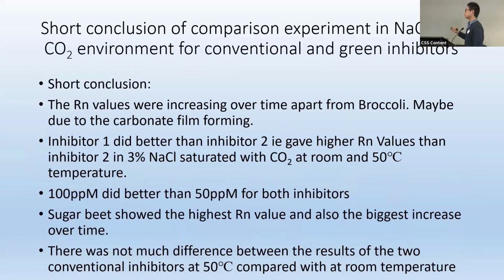So here's the short conclusion, which is like a repeat of things. The Rn value increased over time, probably because a carbonate film was forming during the experiment, and inhibitor 1 did better than inhibitor 2. Higher concentration did better than the lower concentration, like at the 100 ppm level. And the sugar beet did well and got the highest Rn value and the biggest increase over time. And there's not a big difference between the 2 temperatures.